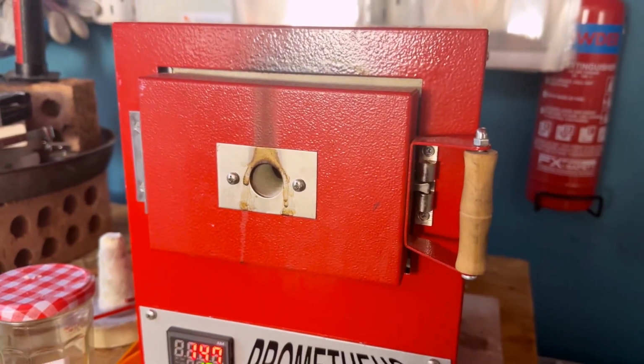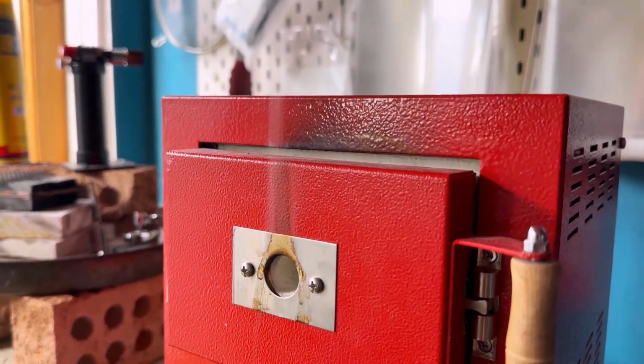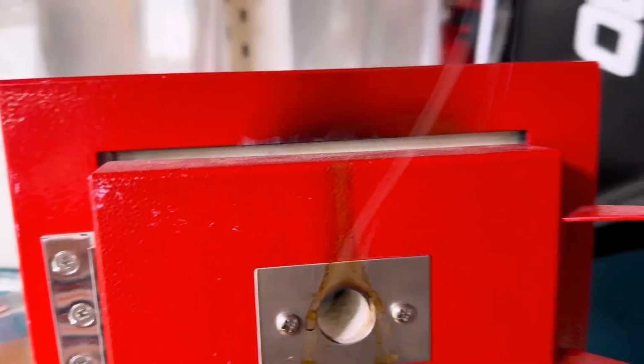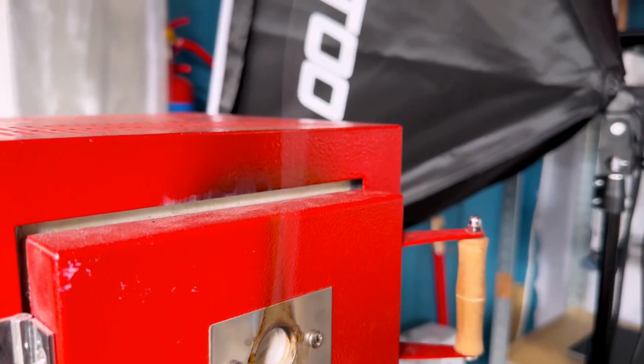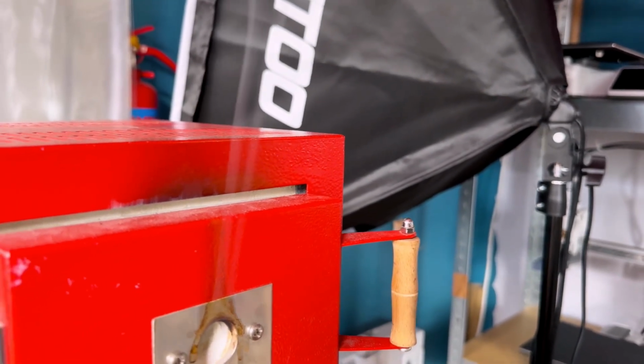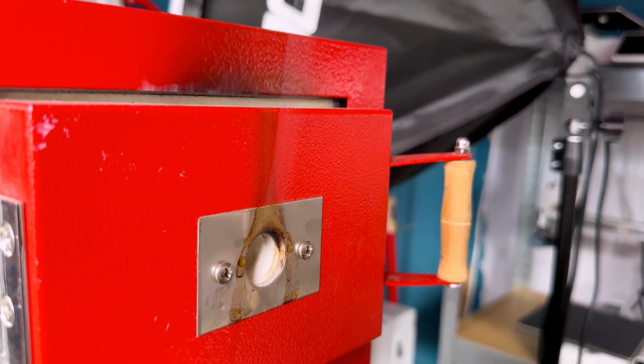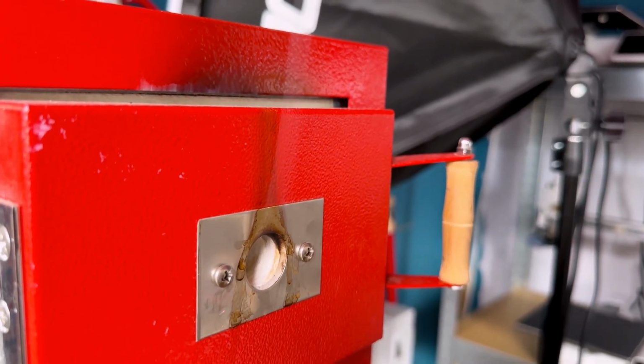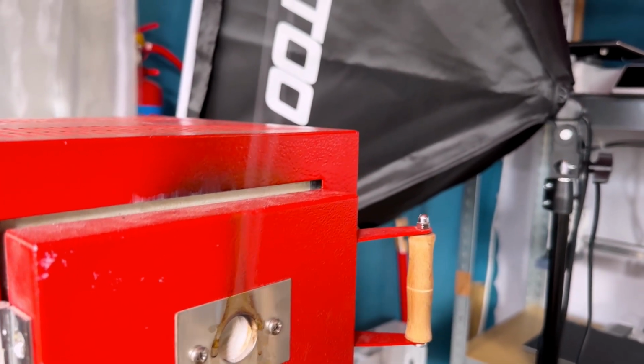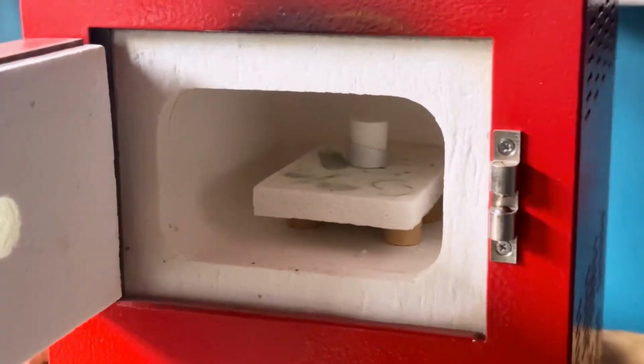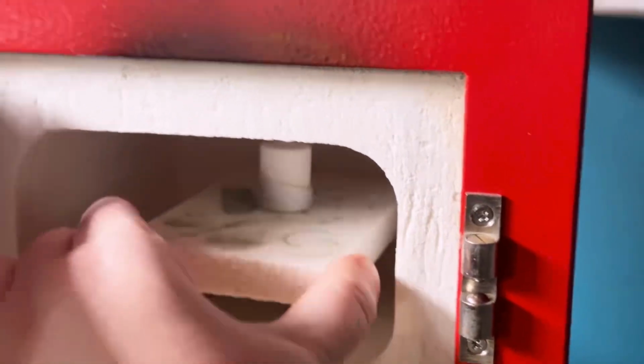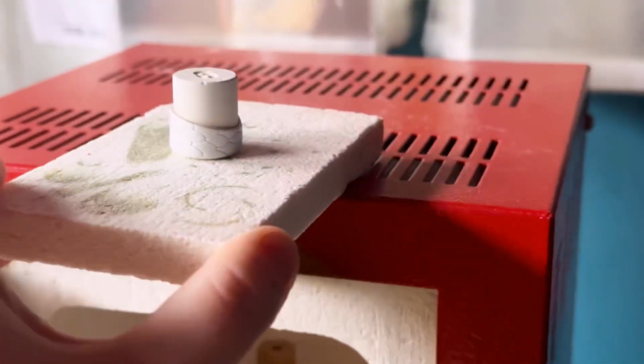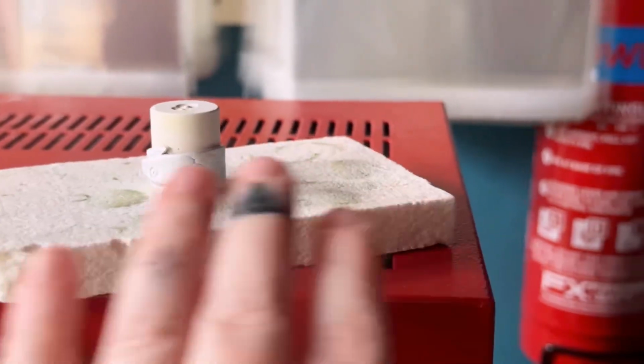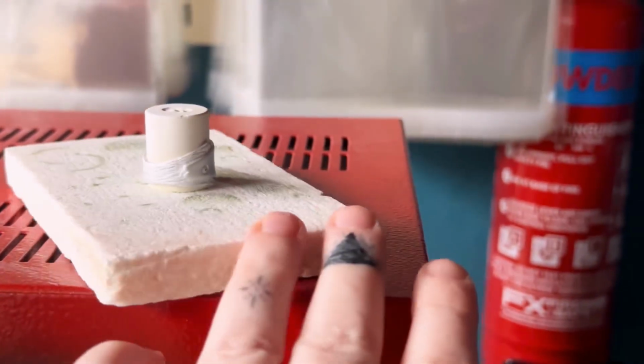At this stage, you might see smoke. This is completely normal. It is just the organic binder burning away. It's always recommended when you're using your kiln to fire in a ventilated area. After the 30 minutes, I ramp up my kiln to 870 degrees and hold for 60 minutes. After the 60 minutes, I switch off my kiln. I leave my piece inside until it's completely cool. Once fired, your ring is now solid silver.